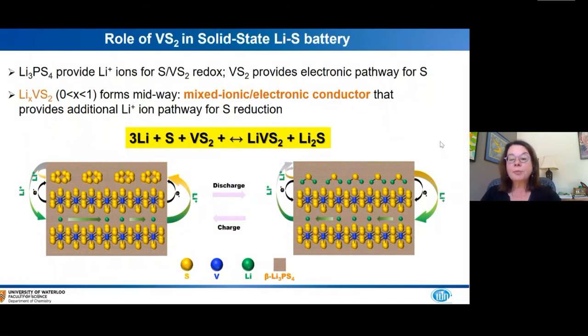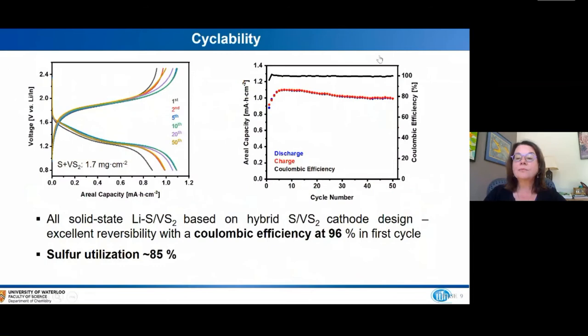The proof is always in the pudding, and in this case the pudding is the battery data. We have here the discharge and charge profiles for the solid state battery. You can see that even on the first charge we have excellent sulfur utilization, with a coulombic efficiency of 96%. We're not at lithium ion type qualities here, but this is very, very good for a solid state lithium sulfur cell compared to the usual values of about 80%. The sulfur utilization we see in the cell is 85%, as calculated from the amount of capacity we see in this cell.